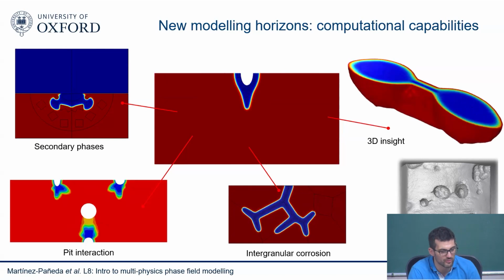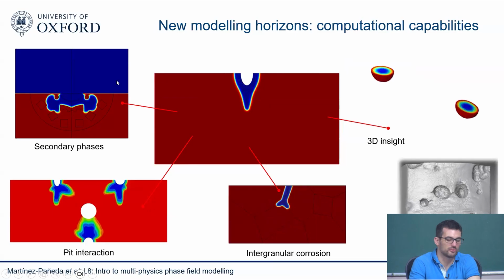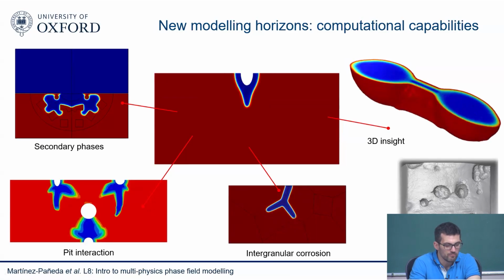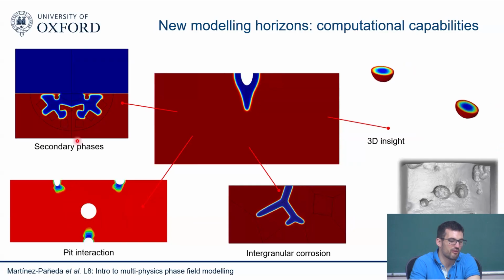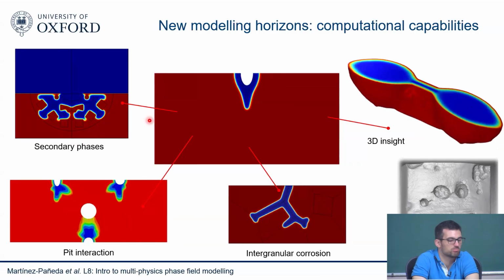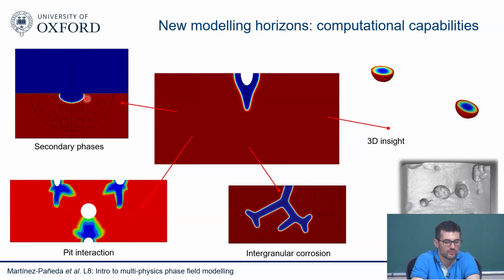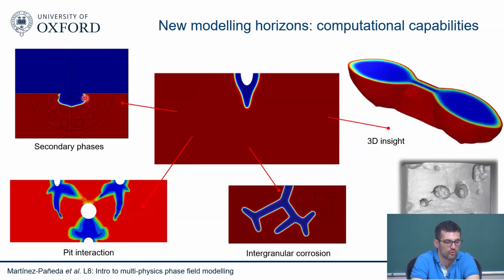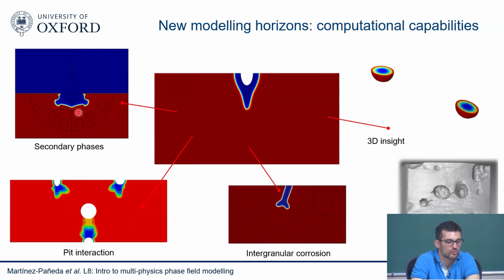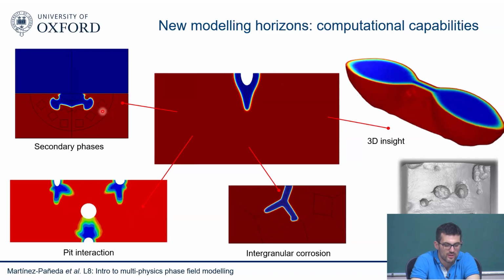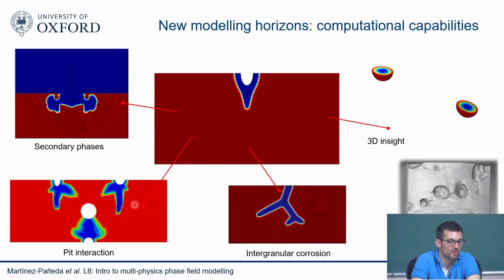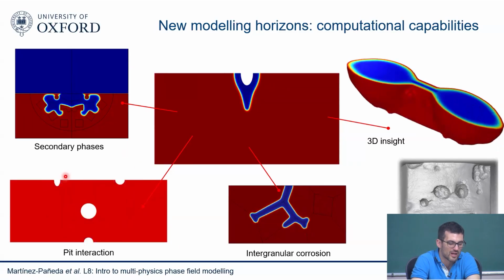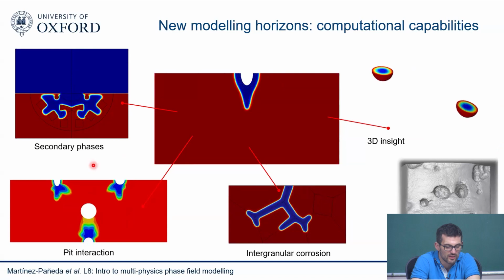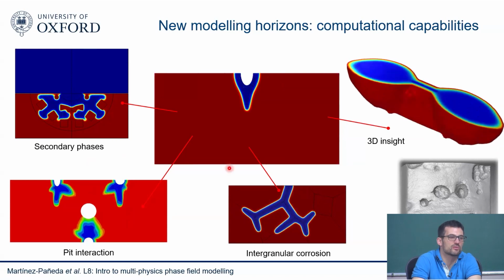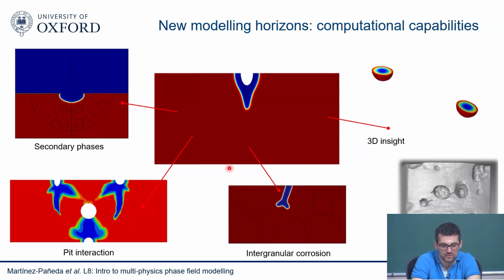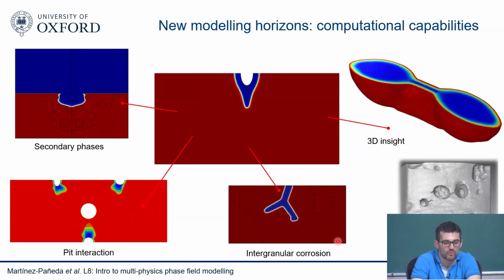And things that people will mention, they will say, okay, from a computational perspective, this is very tricky because you need to handle secondary phases that will not corrode, insoluble secondary phases. We can do that. You can see here how this corrosion front is evolving. These are calculations from our group handling those insoluble secondary phases. They say, oh, you have a lot of pits that can interact. It's very complicated. Well, that comes for free with phase field. You can capture the interaction between multiple pits, no problem. Sometimes you have sensitized grain boundaries, so corrosion will happen along the grain boundaries. Again, no problem. You can simulate intergranular corrosion.